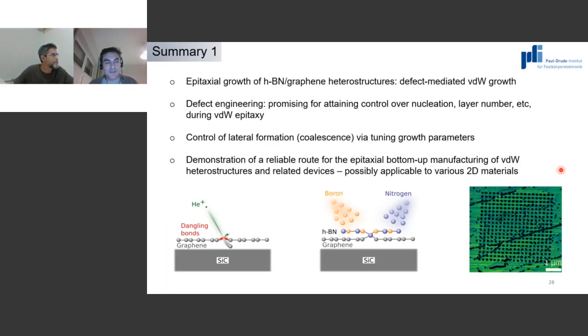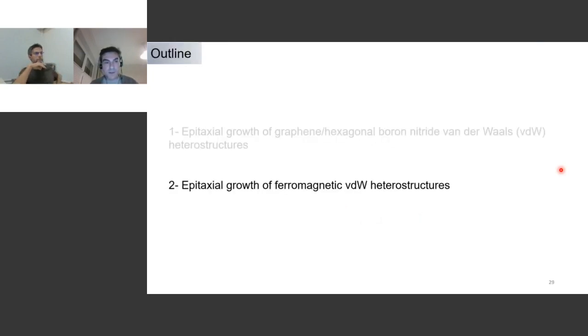Okay, thank you. So this is the first part, epitaxial growth of HBN graphene heterostructures. I've shown you that you have this defect-mediated van der Waals growth. And if you have that, one way that you can actually benefit from these defects is to use defect engineering on your substrate to try to improve growth, to attain control over nucleation and number of layers during van der Waals epitaxy. And we believe that this kind of route is actually interesting for bottom-up manufacturing growth of other types of 2D heterostructures, and we've been trying recently to apply that for other materials.